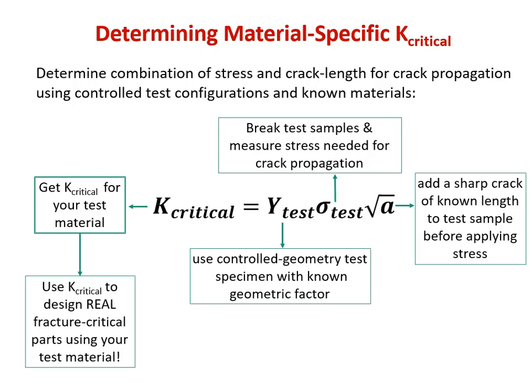It's very valuable. So the way you get this is you design multiple test specimens that have the same Y. So you'll have the same macroscopic geometry, and the same test specimen geometry, especially relative to your loading direction. Many of these are controlled by ASTM standards. There's a lot of different standard fracture samples, compact tensile being one of the most common.